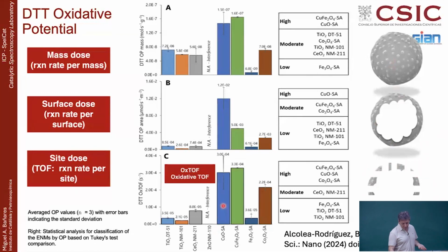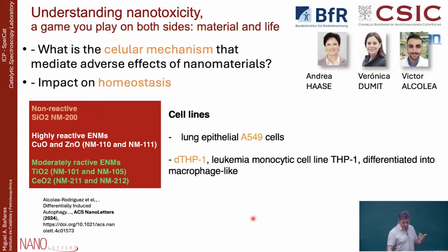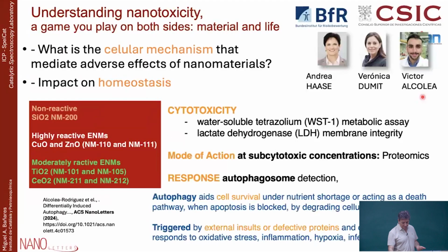And then we found that copper or copper iron had a very high activity per site, the same case as cobalt, but others like titania and silica had very little activity per site. So with the people in Berlin, we sent our postdoc, Victor, to work with Veronica and Andrea, and he was looking at the impact on the homeostasis of the cell, what is happening to them.